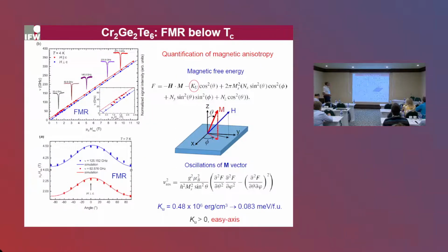Now if we enter the magnetically ordered state, what we observe is that the paramagnetic mode is now split into two ferromagnetic modes, suggesting that we're dealing with an easy axis ferromagnet. You can see that one of the branches has a finite offset here, and the other one softens at a certain critical field. And if one measures the angular dependence, one clearly observes, at different frequencies, a clear-cut angular dependence. Here one has to mention a difference between electron spin resonance and ferromagnetic resonance.